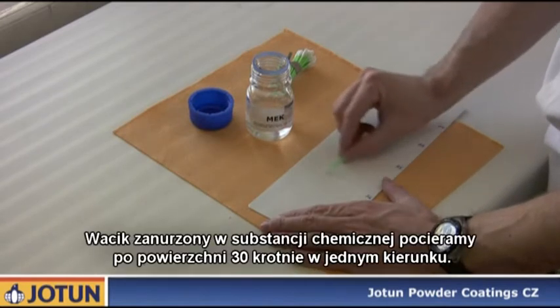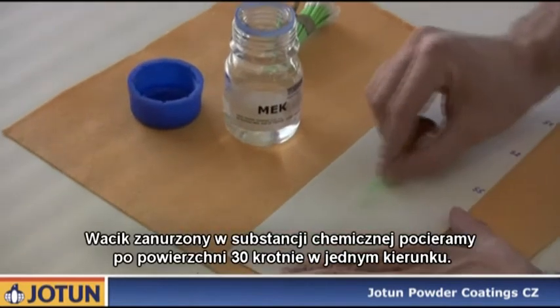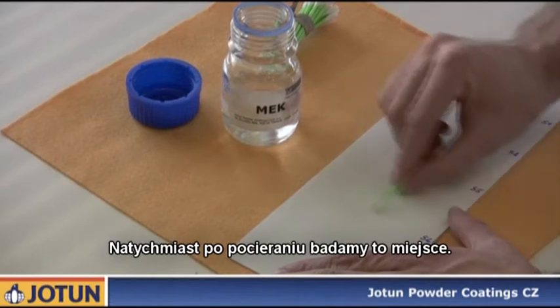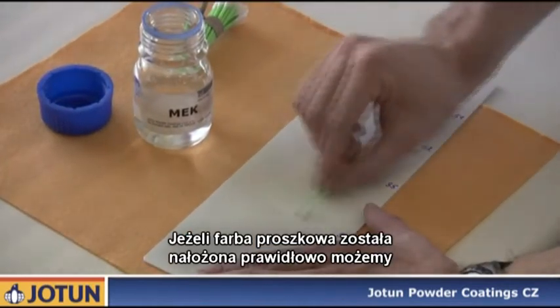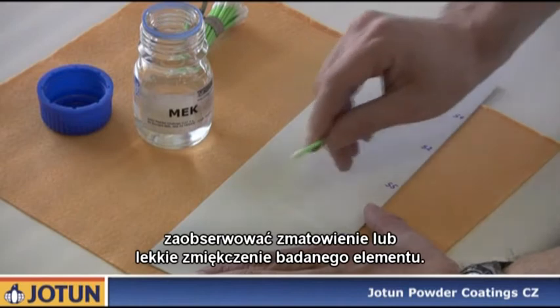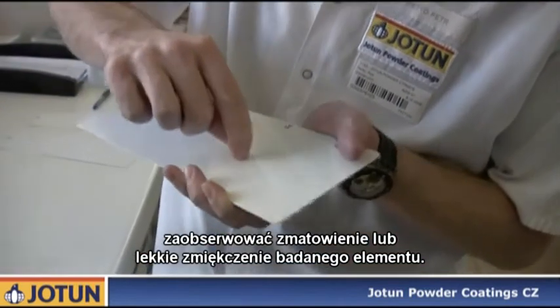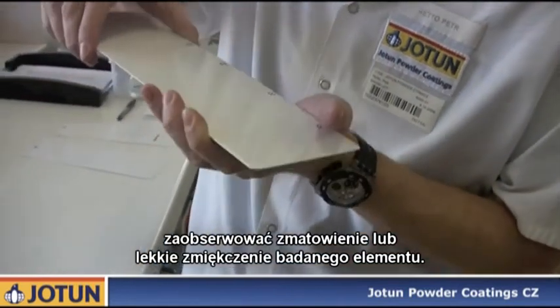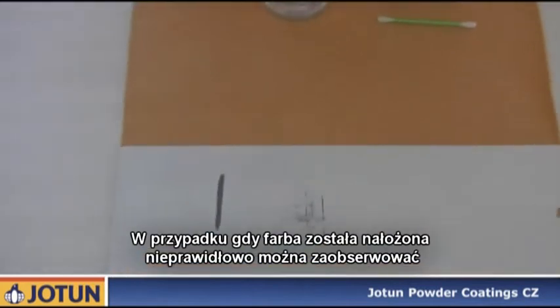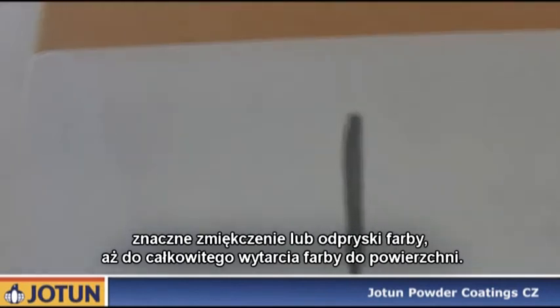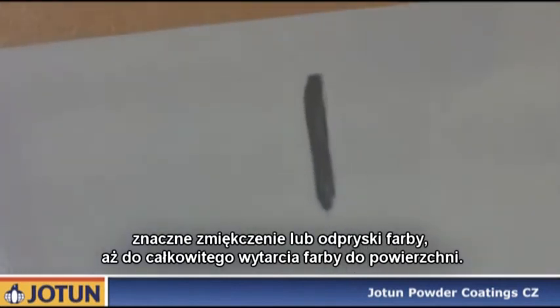We dip a swab in the chemical substance and rub the surface repeatedly. We then examine the rub spot immediately. If the powder coating has been cured properly, we will observe a matting of the surface or slight softening. In the event of a powder coating which has not been hardened thoroughly, we will observe considerable softening and pieces of paint clinging to the swab, and often wipe the paint off the substrate completely.